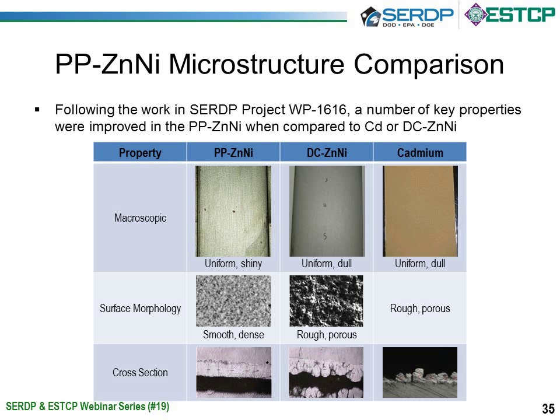So when we look at some of the microstructure comparison, what we found was that the pulse plated zinc-nickel was shiny, versus the DC zinc-nickel, which was dull. Cadmium typically came up as this orange color. The surface morphology was generally smooth and dense with a fine-grained structure, whereas the DC zinc-nickel was rough and porous. When you look at the cross-section, you can see that it's pretty dense and pore-free, whereas the DC process has quite a lot of pores through it, which is similar to the cadmium.